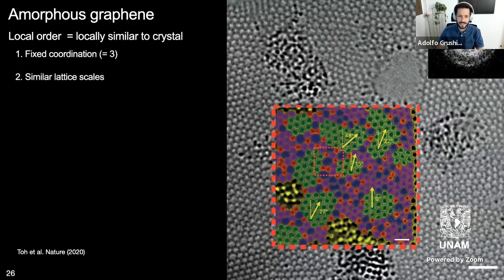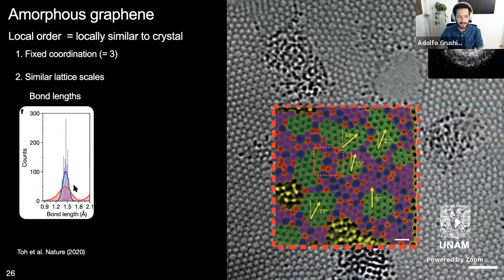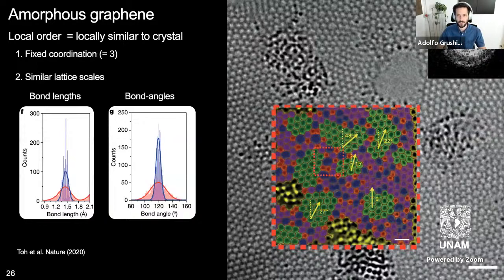And in fact, not only that, it retains a little bit the lattice scales of the crystal. So the bond lengths, for example, are peaked at the values of the crystal. Here the blue is the crystal and the red is the amorphous. You see that the distribution is a bit fatter in the amorphous case, but still peaked at the carbon-carbon distance, as chemical rules dictate. In terms of bond angles, it's pretty much the same story. You have a distribution peaked at 120 degrees, but a little bit fatter for the amorphous case in red. And the last thing that I already highlighted was that there is a little coexistence of amorphous regions around here, and also crystalline regions.